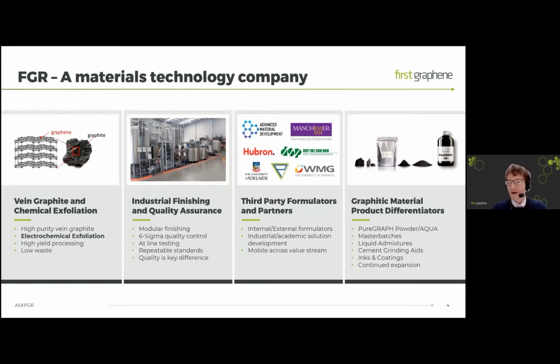We start with very high purity graphite, very low metal ions, very low metal content, very low silicate content. We have our electrochemical exfoliation step, which lifts off those graphene layers from the graphite. We have a very high yield in that process and low waste, and it's really this electrochemical process that's key for the rest of the presentation. We then finish that graphene. We go to our industrial finishing steps, quality assurance.